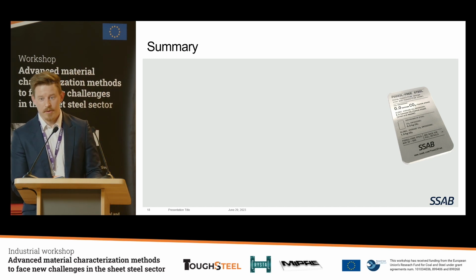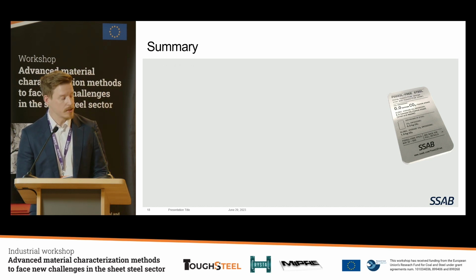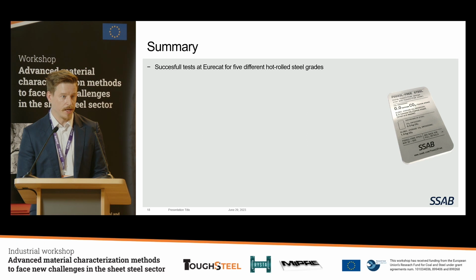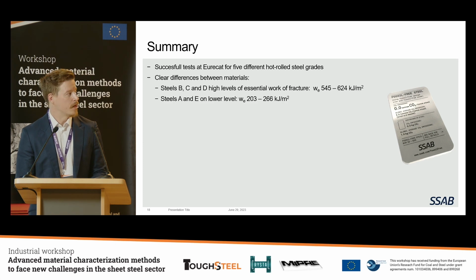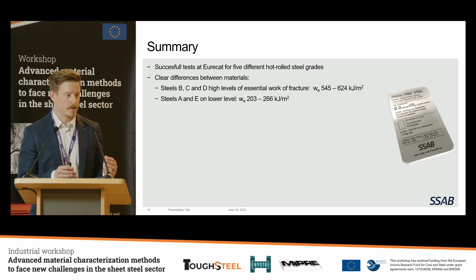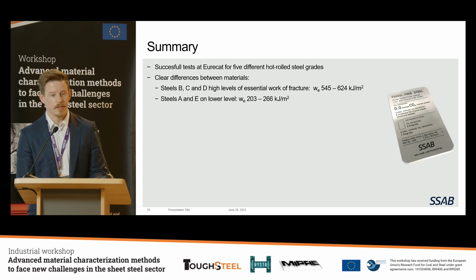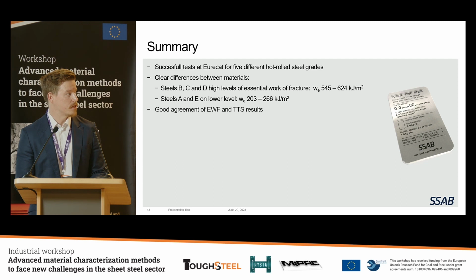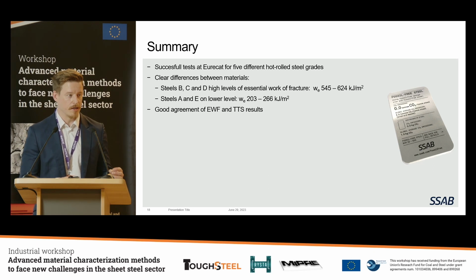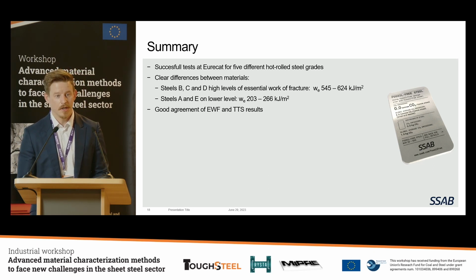Then I think we have time to summarize. We made successful tests for hot rolled grades now in 3 millimeter, also these fracture toughness tests. We could see really clear differences between these materials, two really different levels, and we could rank the materials according to these results. We could see that there is a really good agreement on essential work of fracture and the fracture surface strains, through thickness strains, a really good correlation there.